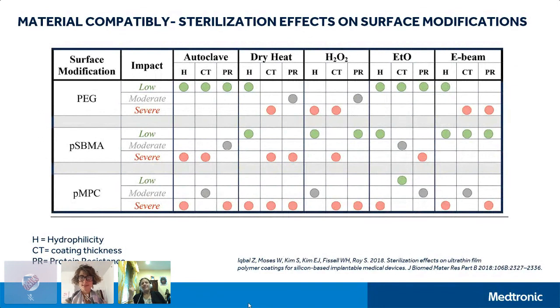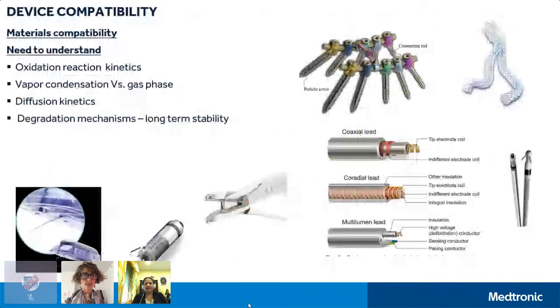peroxide probably doesn't work well with some materials, but the coating here is only a few nanometers thick. So if we are trying to establish a database on devices and surface modifications, this could be a starting point, and then we can expand and build the portfolio of the various modifications that we use, and use it to develop and expand our portfolio.